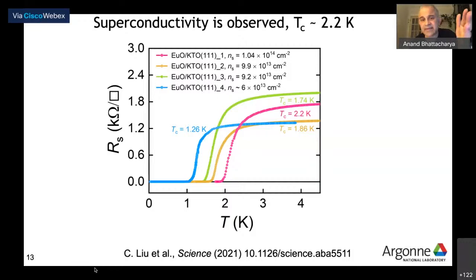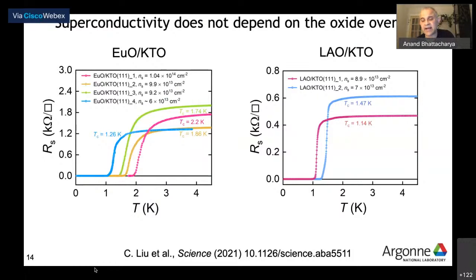The densities from Hall measurements, if you naively interpret the Hall measurements to give you a carrier density, would tell you the densities are between 6 × 10^13 and 1 × 10^14 per centimeter squared, and they monotonically increase in this set of samples. Very early in the game, I was pretty convinced that we had oxygen vacancies or some sort of interdiffusion at the interface, and we tried LAO for that reason, and amorphous LAO gave us superconductivity, at a slightly lower temperature, but it was there on the 111 surface.